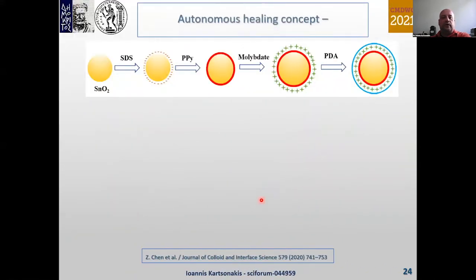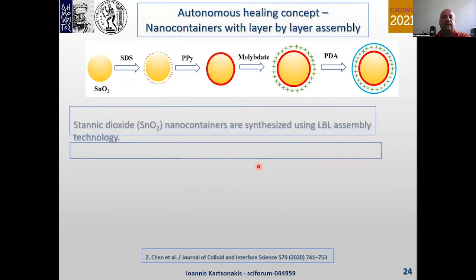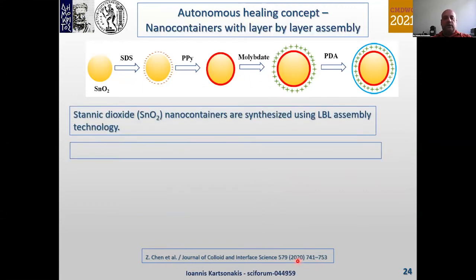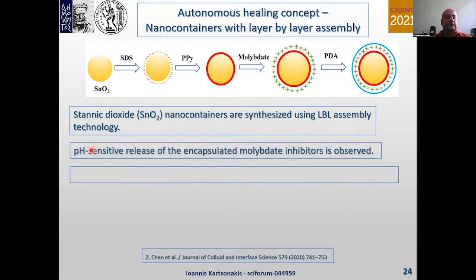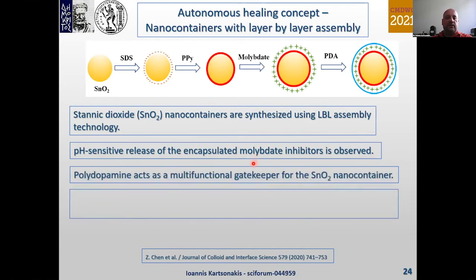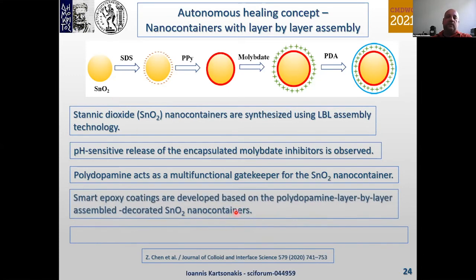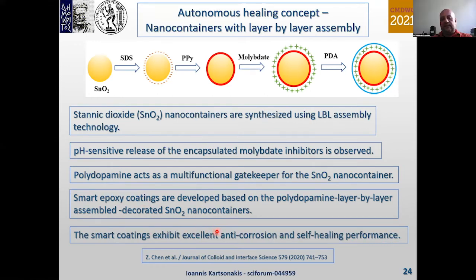So also in the work of Chen et al. 2020, stannic dioxide nanocontainers were synthesized by layer assembly technology. These were pH sensitive because they were fabricated by layer technology. They were encapsulated with molybdate inhibitors, and polydopamine acted as a multifunctional gatekeeper for these containers. They were incorporated into smart epoxy coatings, and this coating exhibited excellent anti-corrosion and self-healing performance.